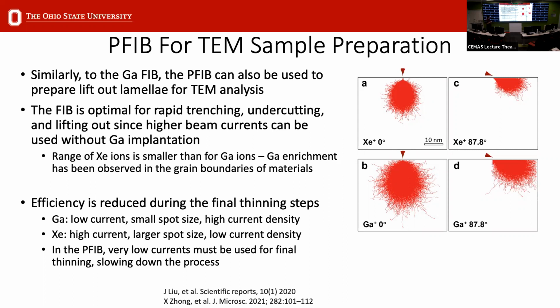But xenon generally has a smaller interaction volume than gallium. So the advantage of the plasma FIB is that you can do your initial steps much quicker. As I mentioned, you can go up to microamps. You wouldn't want to use that for TEM sample prep, but you can typically cut your sample out very quickly.